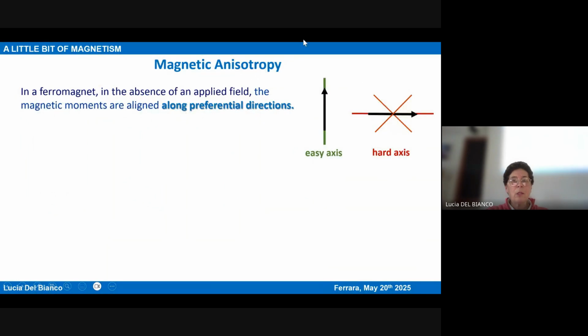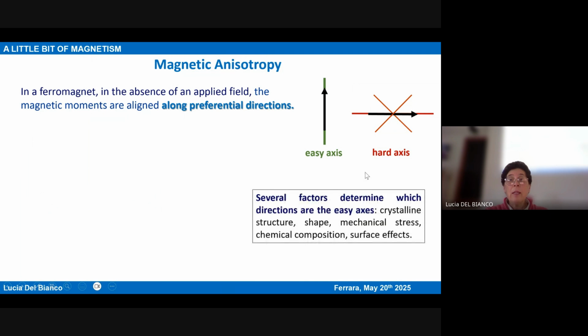This is a key concept of magnetism, very important, which we call magnetic anisotropy. In a ferromagnet, in the absence of an applied field, the atomic magnetic moments, and therefore the total magnetization in each domain, are aligned along a preferential spatial direction, which we call easy axis, or easy anisotropy axis, or easy magnetization axis. And there are several factors which determine which direction is the easy axis. For instance, the crystalline structure, the type of Bravais lattice that your ferromagnet possesses, but also the shape of the sample you are considering, and also the presence of an applied mechanical stress, as I will also discuss later.